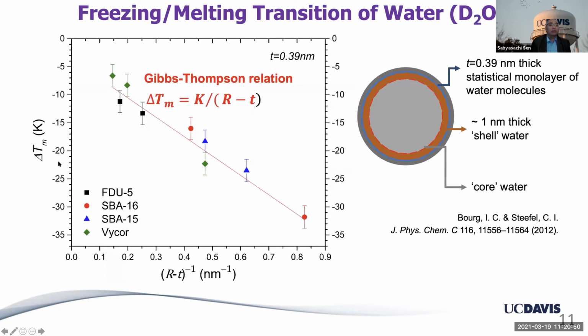Now here is a plot of all these melting point depressions, delta Tm, meaning how far it was depressed. So 0 would be the bulk value. How far it was depressed from the bulk value as a function of the inverse size of the pore space. And here you can get a nice relationship using a slightly modified Gibbs-Thomson relation, which is this, where in the denominator is not purely R, but R minus a thickness, which is a typical modification of the Gibbs-Thomson relation, which takes into account a thickness